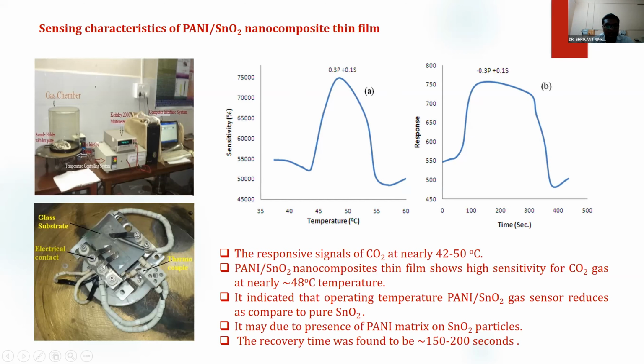So I measure the sensitivity of that glass substrate of PANI SnO2 nanocomposite with increasing temperature. As I increase the temperature from normal temperature up to 80 degrees centigrade, simultaneously I measure the changes in the resistance by using the Keithley 2000, which is the model number of that meter. I calculate the sensitivity as Rg, the resistance when I supply the gas, minus Ra, the resistance in air. Then I remove the gas from that chamber and place clean air into it. That means I get two readings: the resistance after supplying the CO2 gas, and the resistance of the sample after supplying clean air. By using this, I can find the sensitivity of the material.